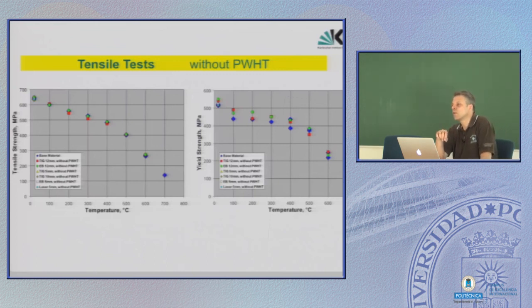To test these Eurofer welds without heat treatment by tensile test is completely useless. You could already have predicted the results, because what happens? Without heat treatment, you produce in any case hard martensite, and this is a very strong material, and it will never break in the weld, cannot, because the base material is much softer, so it always fractures or breaks in the soft area, in the base material area, and so in the end what you are testing is the base material, and that's why here all dots show the same line, regardless whether this is unwelded Eurofer or welded Eurofer.